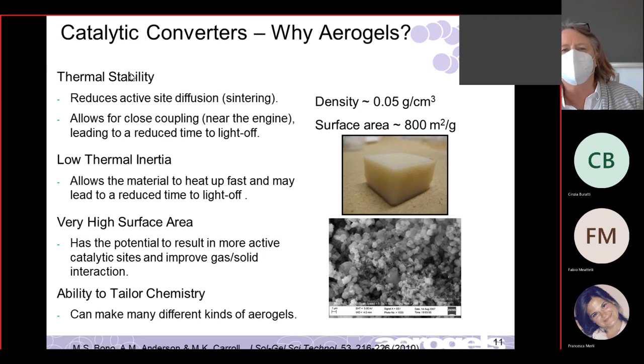So that being stable means you could reduce, when you impregnate the material with whatever catalyst, whatever metal, when it gets hot, it sinters, and so the particles agglomerate. So if I have a bunch of nanoparticles, suddenly they become bigger particles with temperature, and that's not necessarily good.